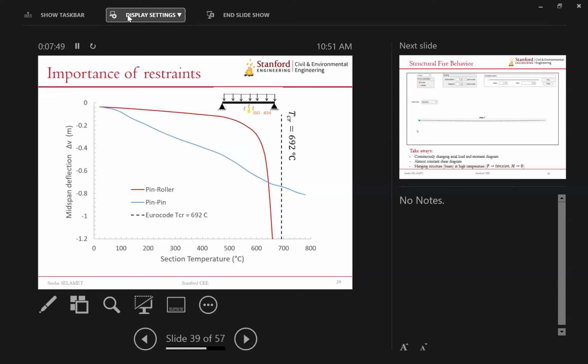And Eurocode, just as a side note, you can do back of the envelope calculations and find out the critical temperature to be approximately 700 degrees for this particular problem, the cross section and the length. And you can see that the analysis is not too far off, or vice versa, the code is not too far off in calculating that runaway behavior.